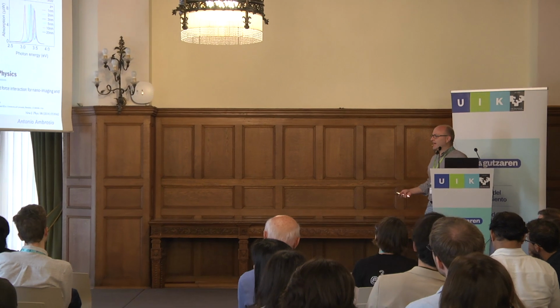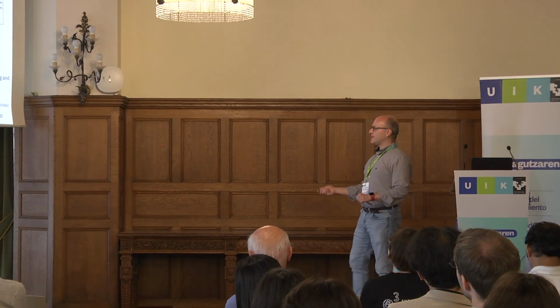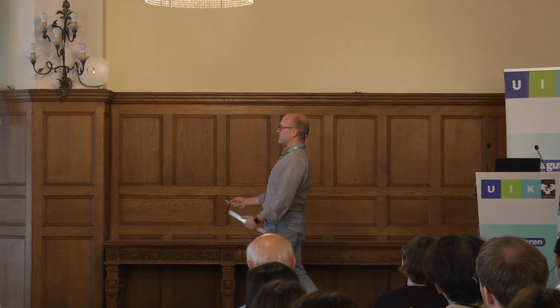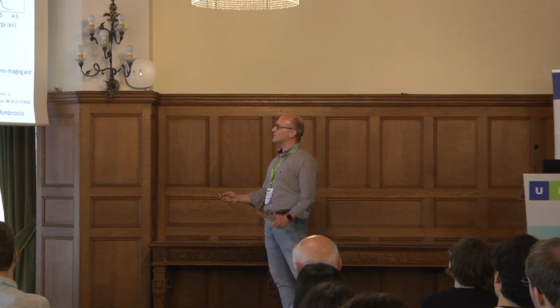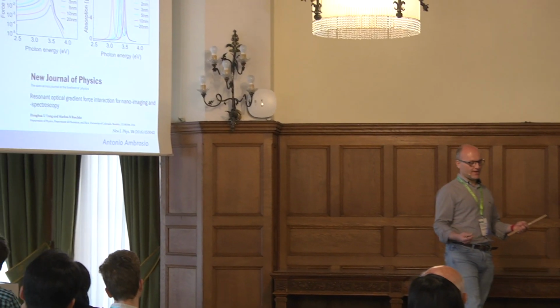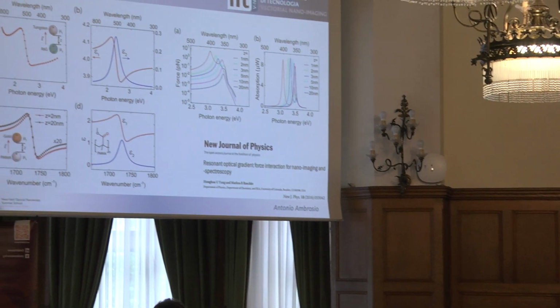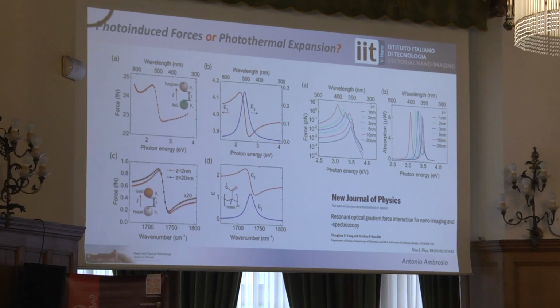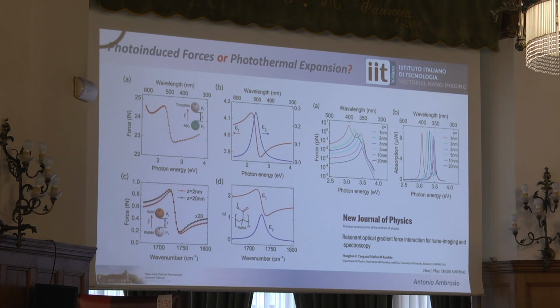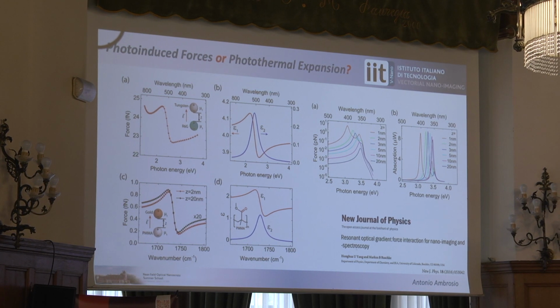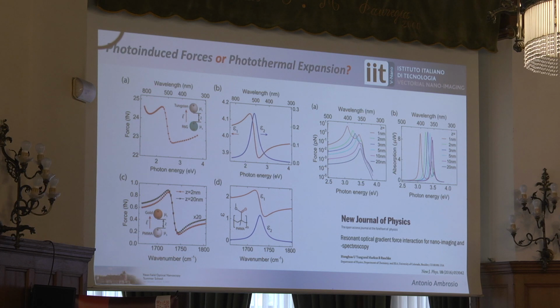Of course, people tried to go in favor of one or the other. So there is one paper from Markus Raschke, for instance. He tried to prove in this paper that it depends very much on the symmetry of the spectrum that you get. If it's symmetric, that means that it's more absorption, right? Because K goes symmetric. If it's asymmetric, it will resemble more the real part, and then it goes more in the photo-induced part.